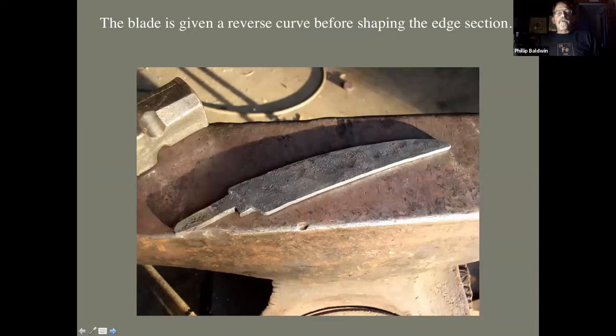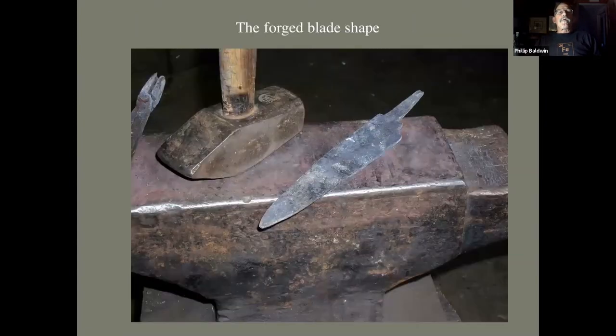Okay, reverse curve to account for making the edge thinner and the blade bends backwards. This has changed a little bit. Since then, I figured out a different way of forging blades. So a reverse curve is less important. I found that using the cross peen of the hammer to taper out the edge is actually a lot more efficient than using the flat of the hammer. Next slide. Forged blade. Next slide, please.